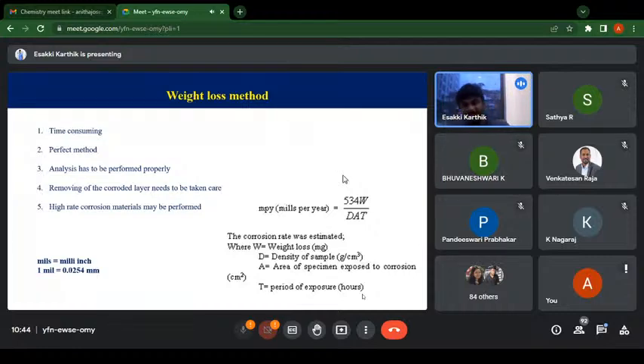Once you know the weight loss, this is the equation that is called mils per year. 1 mil is approximately equal to 0.0254 millimeter. Mils per year means how many mils you are losing per year due to corrosion. W is how much weight loss you are seeing. 534 times W divided by D, the density of the sample, whatever sample you are taking, A is the area you are using, and T is the period of exposure, how long you are keeping your sample. With this, you can find out the rate of the corrosion.